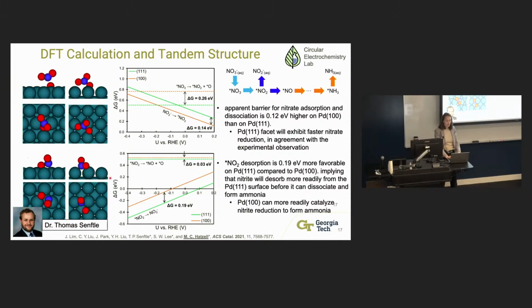His group is actually a leading expert in understanding specifically nitrate and nitrite reduction. And so what his research group did was look at the adsorption energies for nitrate and nitrite on these various controlled facets. And really what he was able to show was that nitrate adsorption and dissociation was 0.12 eV higher for palladium 100 over palladium 111. So basically, why we were getting better nitrate reduction was really just due to this decreased adsorption energy.